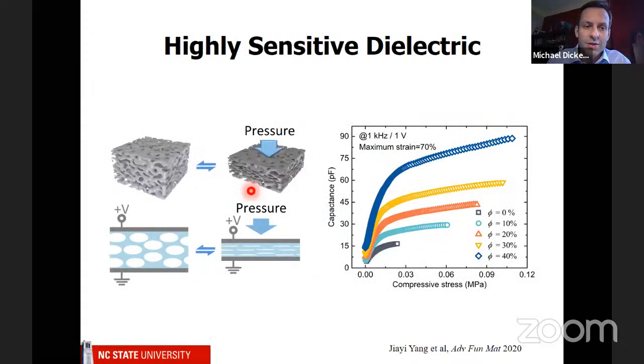So we wanted to see if this works. And again, here is our foam. We push on it and we measure the capacitance when we press this foam back and forth. So here's the capacitance plotted as a function of stress. That's how hard we push on the material. And we see that the capacitance goes up. Now there's a family of curves here, and this represents no liquid metal. So you can see down here, the signal is very low. And then this is 40% liquid metal, which gives us very good signal. So what we've effectively done is increased the dielectric constant and made it a really good sensor.